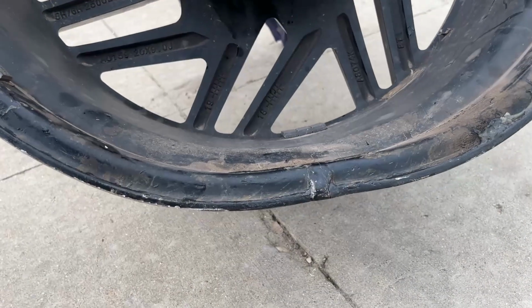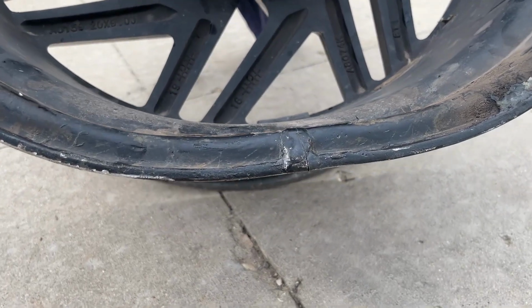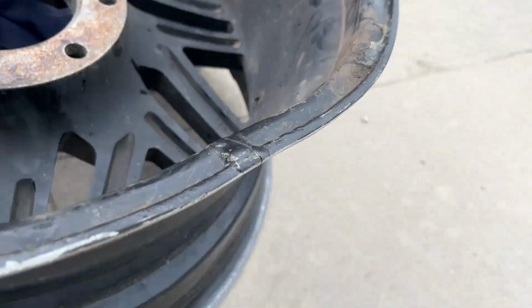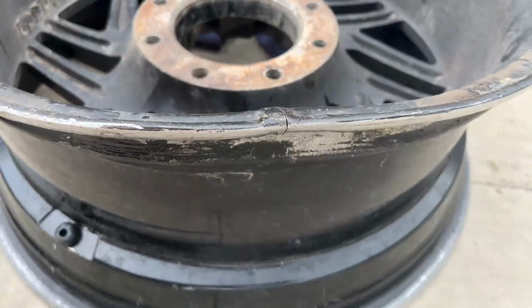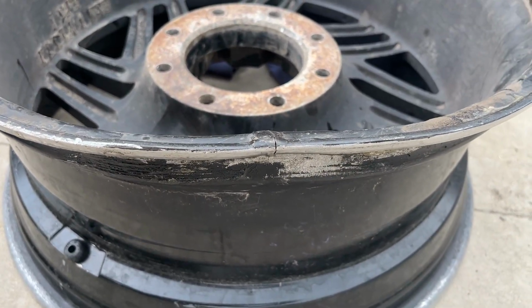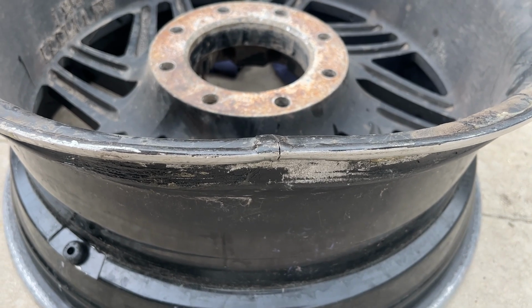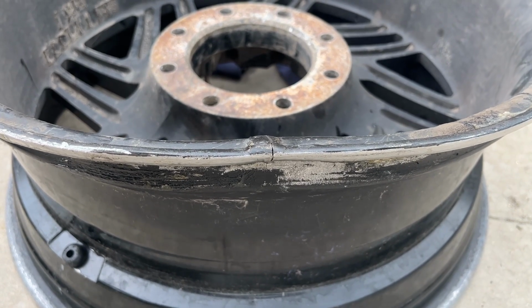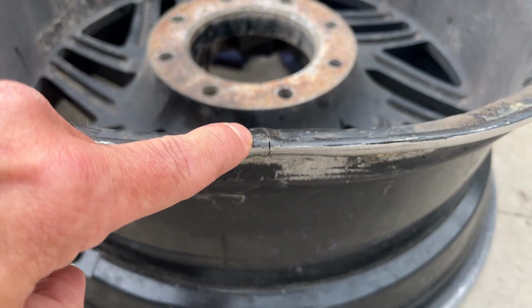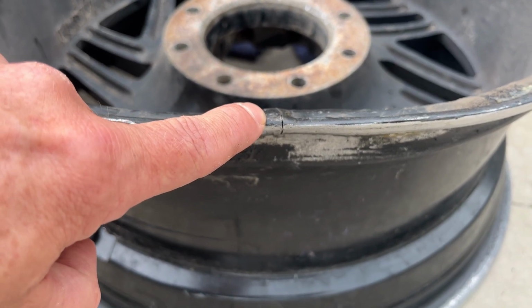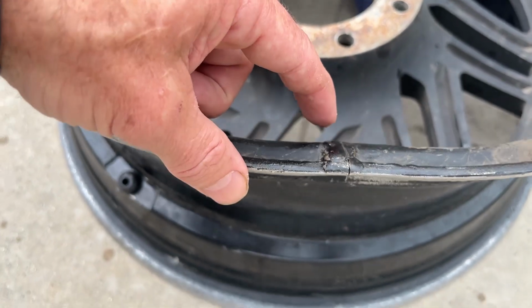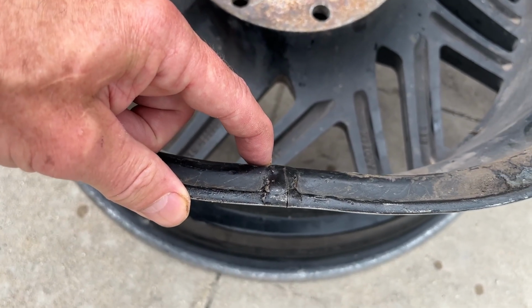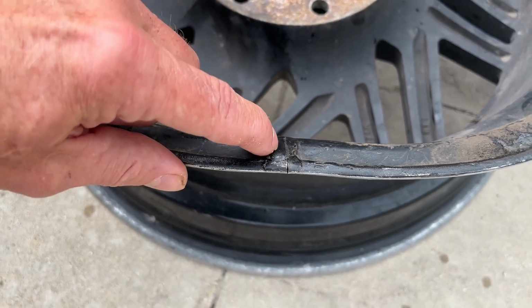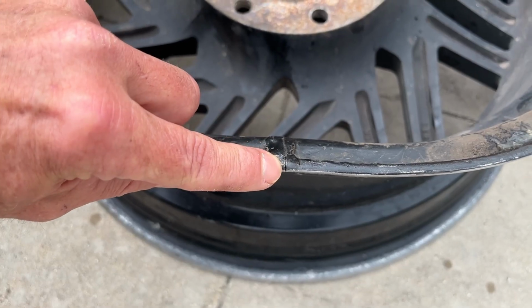So here's that crack right there, right through the bead seal. You can see it definitely has opened up. And to me, that's a classic sign of either a solidification crack that occurred during welding, because that's how aluminum fails and that's how it's going to crack, or it's possible that they also didn't drill out the end of the crack initially and it allowed that crack to propagate again back to that weakest spot. So let's recap why that initial weld repair might have failed again in the first place.